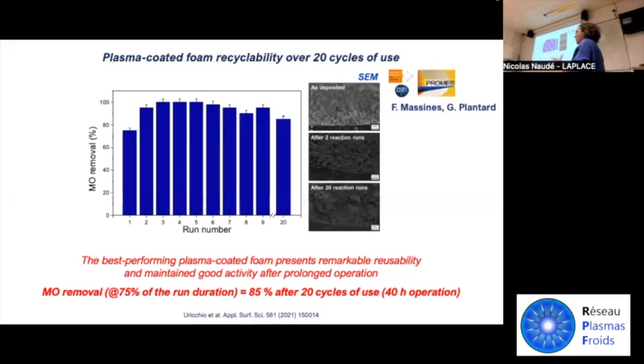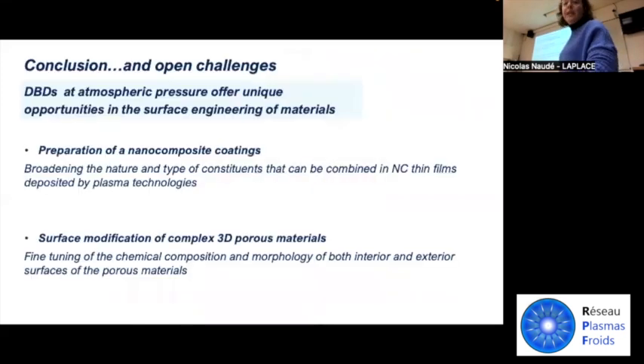Let me point out that in the literature, many photocatalytic materials are reported, but very often the characterization of the material and the stability of the material is tested from 1 to 5 reaction cycles. So we were really able to understand if the coating is really able to withstand the reaction and what we can improve. So let me move to the conclusion of this talk.